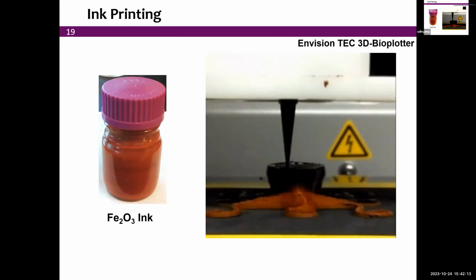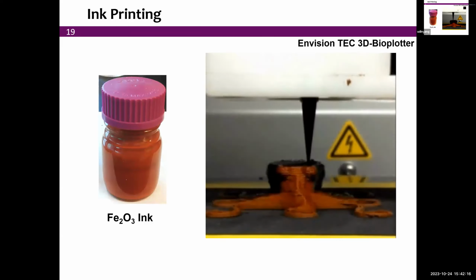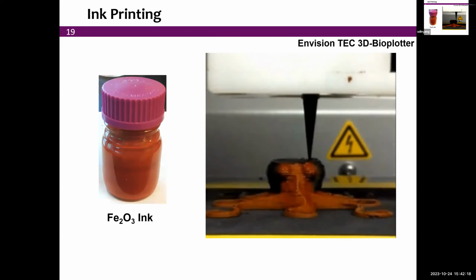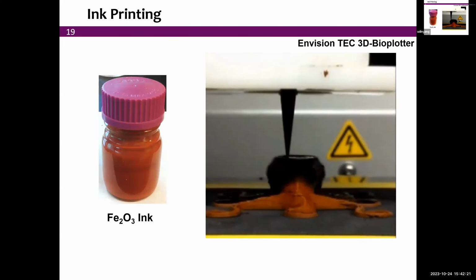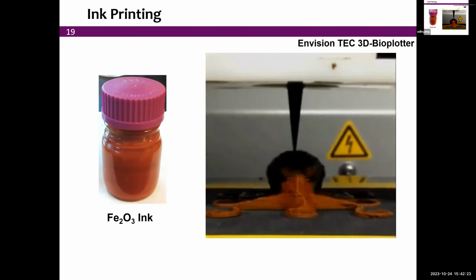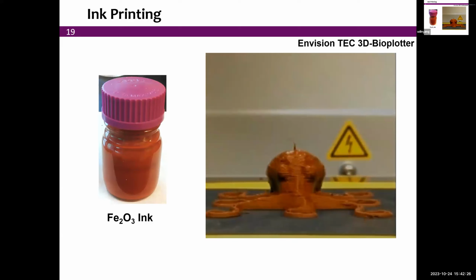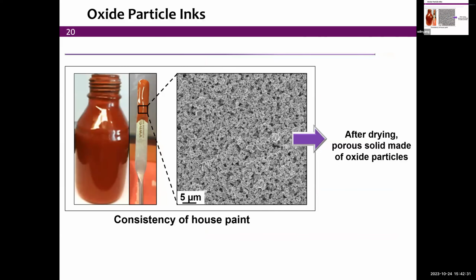So this is of course accelerated here, but you see, for instance, an iron oxide ink that is essentially rust, high purity rust, and you can really create, in that case, a demo piece, a little octopus out of the oxide, which will then be reduced to pure iron. If you look at the particles, they are clearly submicron. They're also clearly closely packed after the extrusion. So after drying, you have this porous solid that is strong enough with a little bit of binder that it can be handled without fracture, and so we can go and do the sintering.